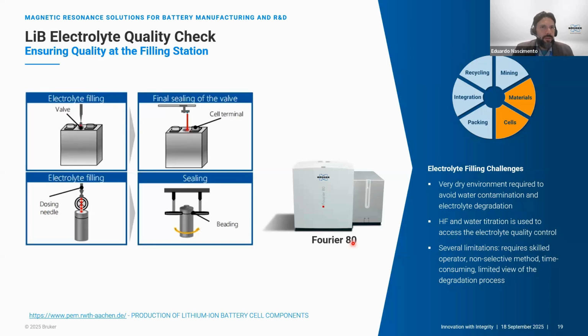From my personal point of view, I think the biggest limitation of this technique is the fact that it's a limited method, because you are only, in the best case scenario, quantifying or seeing water and HF. And when you have highly advanced methods like NMR, you can see a lot going on in terms of the degradation process.